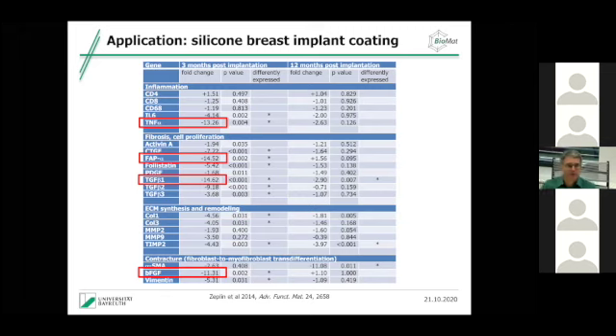So we tested a lot of factors, first in rats, then in humans, and you see that most of the inflammation factors go down. So this is always in comparison with the non-coated silicone implant. You see that a lot of factors are dramatically reduced. There's only one factor, the CD4, that is slightly increased. But if you look at the factors, all the others are negative, which means they're all much lower than in the uncoated control. Inflammation factors, fibrosis factors, TGF-beta1, which is a very important marker for capsular fibrosis, severely reduced. Contracture markers, fibroblast to myofibroblast transdifferentiation, so this is an indication of wound healing, pretty much reduced.